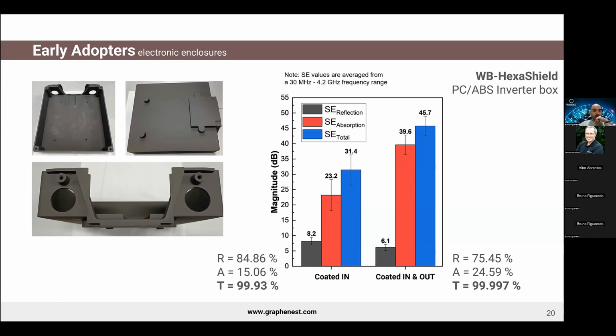As you can see on this plot, I'm also showing the shielding effectiveness and the two contributions of absorption and reflection for the two scenarios, coated inside only and coated inside and outside. Basically, to perform the shielding tests, we used the lid of the box, and we put the lid of the box in between the waveguide. That was how we measured these numbers. As can be seen, by coating only inside, we were able to attain 31 decibels of total attenuation, and this value increases up to 45 dB when both sides were painted. And what was interesting to see was that the reflection mechanism decreased a little bit and the absorption increased a little bit as well.